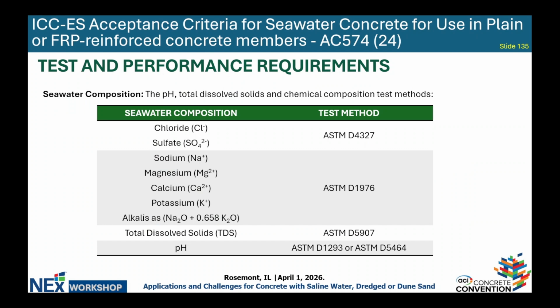Okay, so the first testing requirement is the chemical composition of the seawater. And so to test the chemical composition of the seawater, we are requiring the following standards. So for the chloride sulfate content, ASTM D4327. For the sodium, magnesium, calcium, potassium, and other alkalis, ASTM D1976. The total dissolved solids is D5907, and then the pH can be measured either with D1293 or D5464.